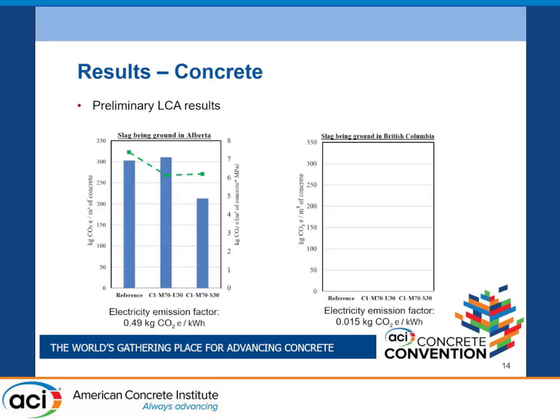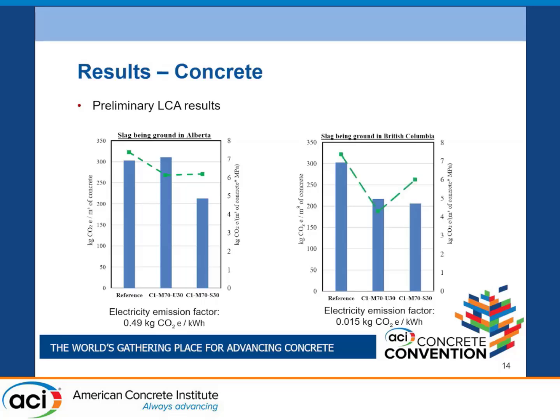But if we do grinding in other provinces which have a lower GHG emission per kilowatt hour of electricity, we will see a decrease in the GHG emission of our concrete. And again, if we normalize it to the compressive strength, the amount is much lower.